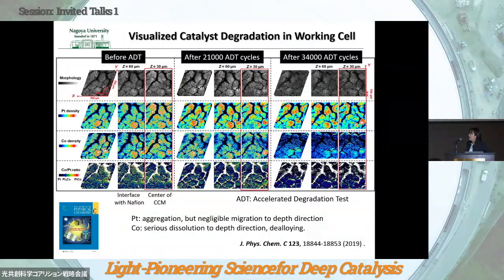So this is an image before the ADT, the cross-sectional image, and after the accelerated degradation test process. This is the middle stage of ADT, and the final stage of the ADT. We can see the change in the distribution of platinum and cobalt catalyst, and also the change in the valence state and the chemical structure of these catalysts at each stage. For example, for platinum, you can see the small aggregation in the cathode catalyst layer.